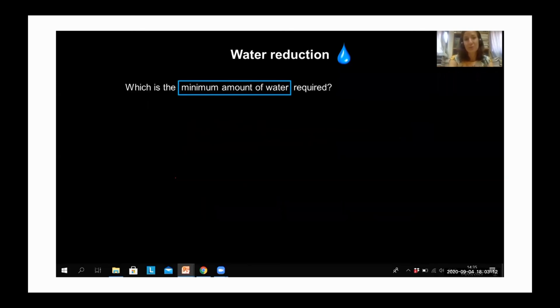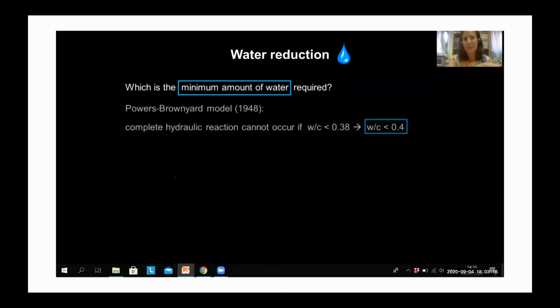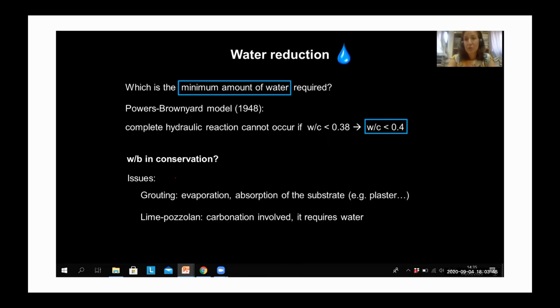So basically, it needed to be understood what's the minimum amount of water which is required. Well, in hydraulic reactions, we know from previous research that the minimum water to binder ratio, this is w/c because it's water to cement ratio, was studied for cement, which is a hydraulic material, as you know. The water to binder ratio shouldn't be lower than 0.4. And also, I need to point out that water is needed not just for hydraulic reactions, but also for carbonation, because water needs to solubilize the CO2 for the reaction to occur, and also the calcium hydroxide needs water in order to